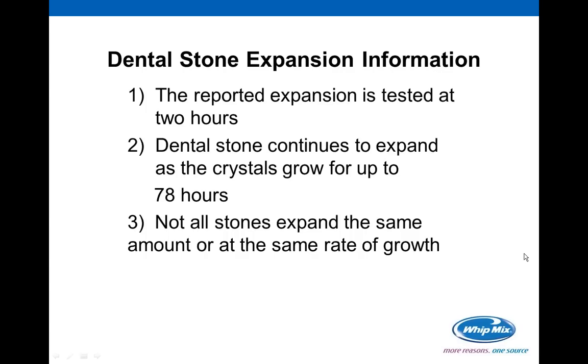Now, let's talk about dental stone expansion information. First of all, when dental stone expansion is reported, this is a report that's done at a 2-hour test. So 2 hours from the point of mixing the correct water-powder ratio. 2 hours later, the test is completed, and that is the expansion for that particular dental stone that is reported in the literature.